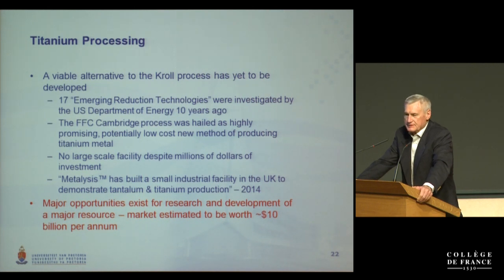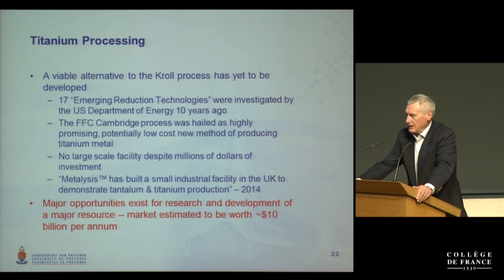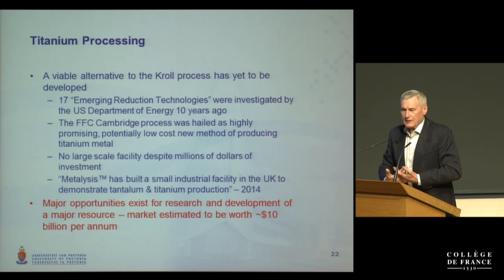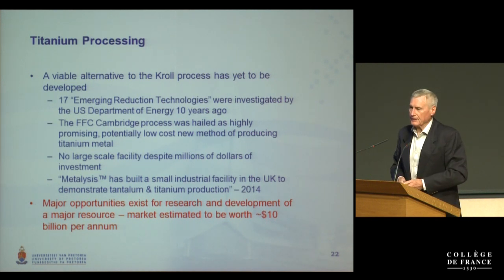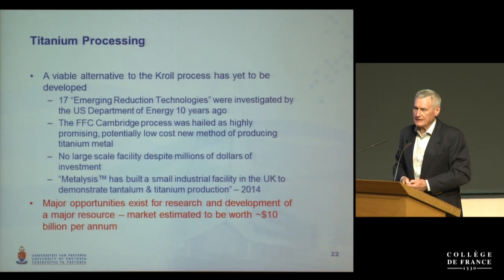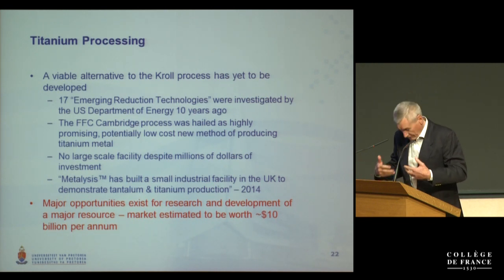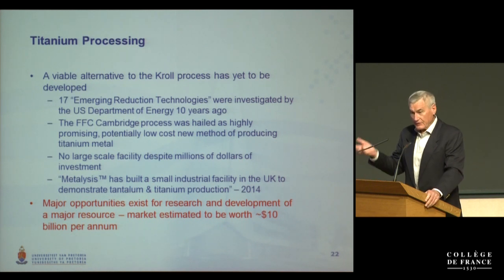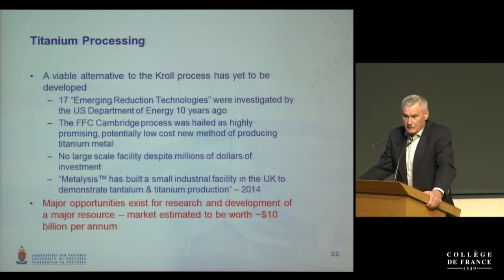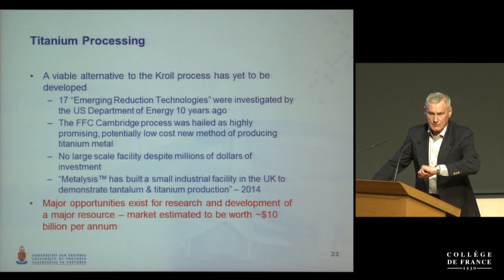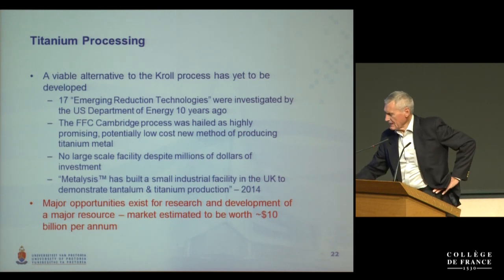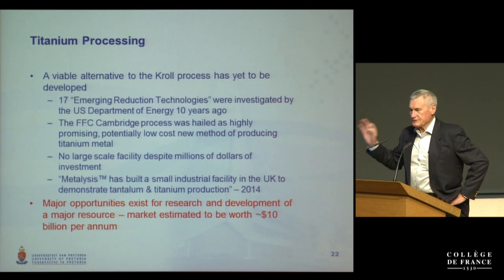Probably the most promising one is the so-called TiRO process of the CSIRO in Australia, where they're trying to make this process continuous and producing below the melting point of magnesium chloride, a fluidized reduction of the titanium tetrachloride. Then that's treated further, but it's a continuous process. How am I doing? 5 minutes. So there's a lot of research opportunities in this area.